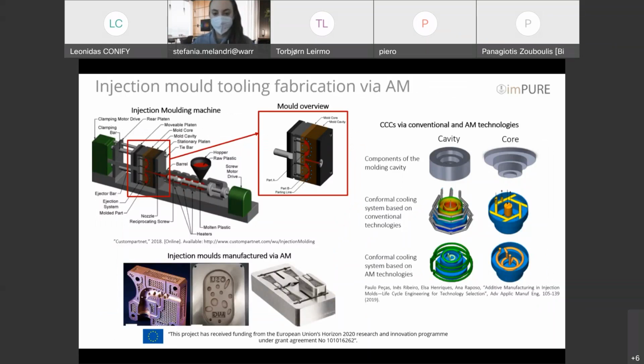So the next step was to look into the actual mold fabrication via additive manufacturing, and in our case, we were interested in the mold core and the mold cavity. Our goal was to take advantage of the freedom of design that additive manufacturing has to offer, and specifically with DED, we can manufacture big, more bulky parts, at least when compared to laser powder bed fusion, or in general powder bed fusion additive manufacturing. So we can exploit this freedom of design in order to create, for example, conformal cooling channels. As you can see in the image here, you have both the cavity and the core. And essentially, you can take advantage of conformal cooling based on the freedom of design that AM has to offer, and create some innovative solutions and designs that might be efficient for the fabrication of molds. So in our case, next slide, please, Stefania.